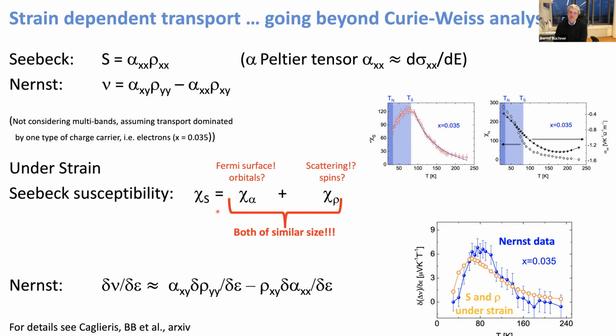And if you do that, and this may be relevant for this doped compound, you can determine a Seebeck susceptibility, which is a sum of a susceptibility coming from this Peltier tensor, and this is something which is really measuring details of the Fermi surface usually, plus a second contribution, which comes from the resistivity. This is the susceptibility from the resistivity, which I've shown you earlier. And you can do this analysis, and then you find out that you definitely need two kinds of susceptibilities. You cannot take the resistivity values to explain the Seebeck effect. That's also already clear from the concentration dependence, and both of them have similar sign.